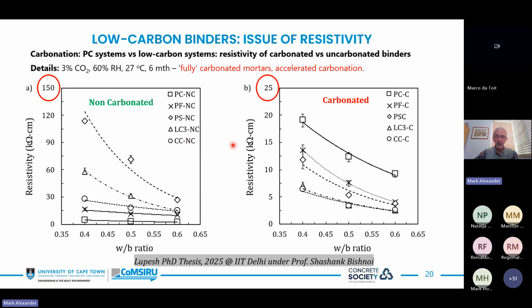Here's some very interesting work coming out of IIT Delhi under Shashank Bishnoi, where they took fully carbonated mortars at 3% CO2, accelerated carbonation testing. Here are the parameters of the test, the environment of the test. Bear in mind that these are fully carbonated, and we're looking at resistivity in kiloohm centimeters. On the left here, non-carbonated, on the right, carbonated. And look at the scales. Resistivity here up to 150 kiloohm centimeters, on the right 25.